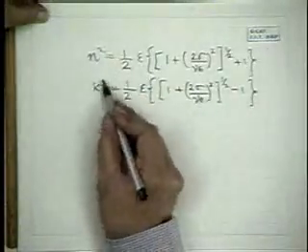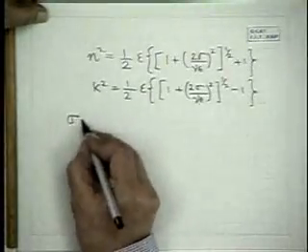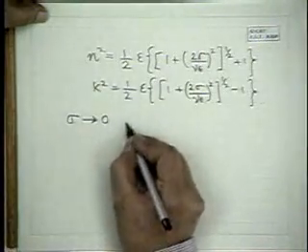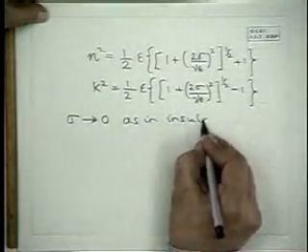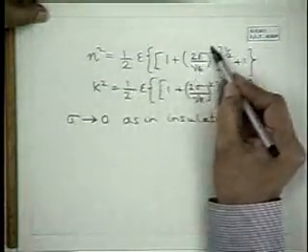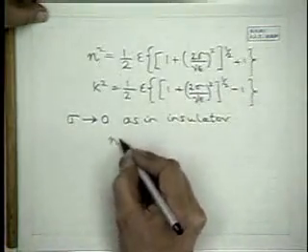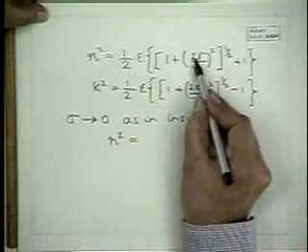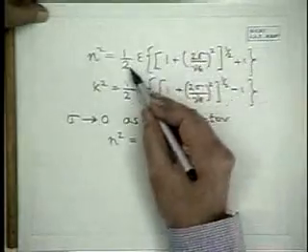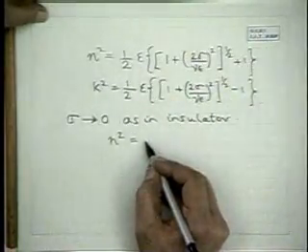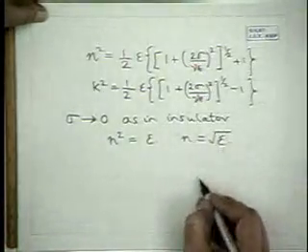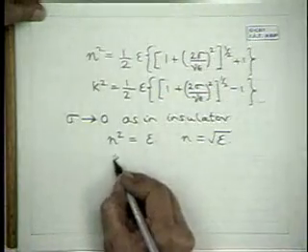So this is the real part, this is the imaginary part, and you can see that when sigma, take the case when the material is completely insulating, non-lossy, a perfect insulator, this term goes, okay, you have n squared, there is a 2 sigma squared, you take the root, you get a 2 sigma, this cancels, so n squared is equal to epsilon, right, or n is equal to root epsilon, and k tends to 0.